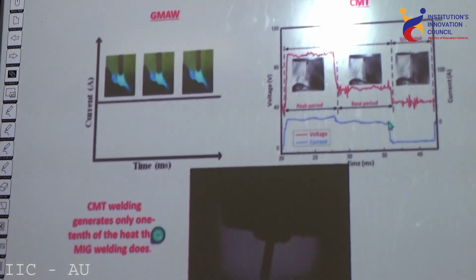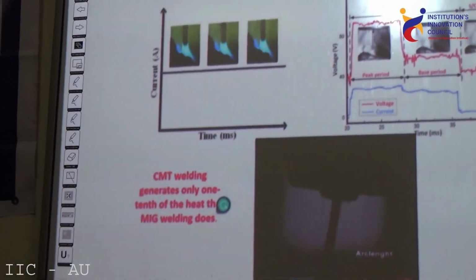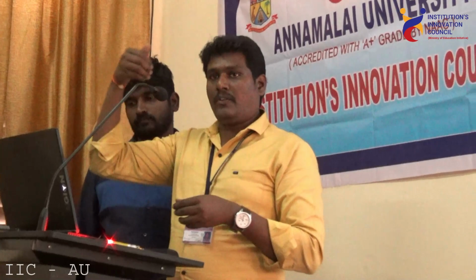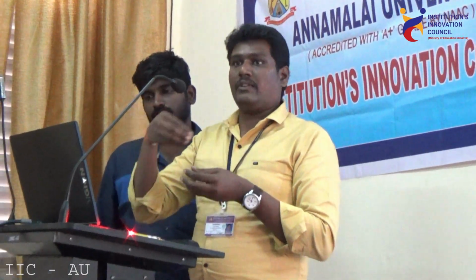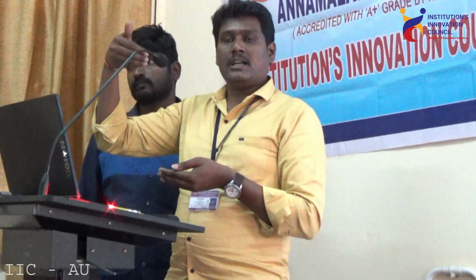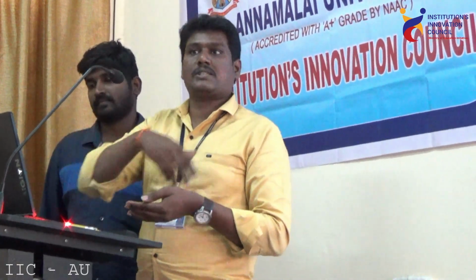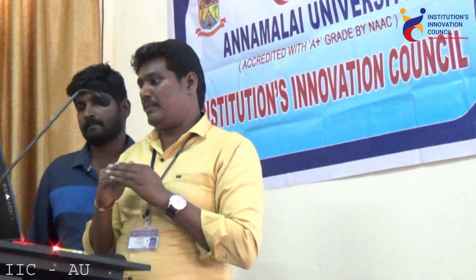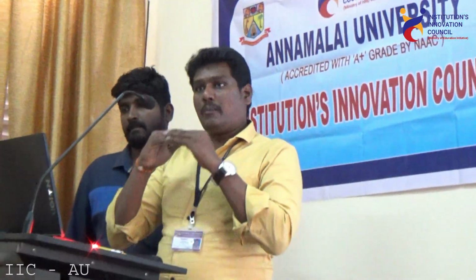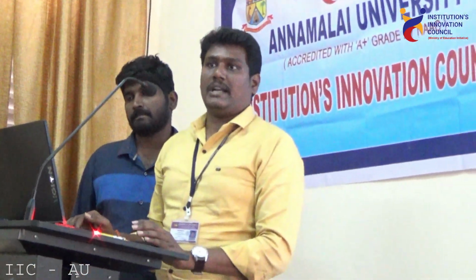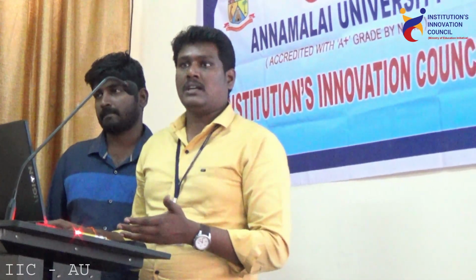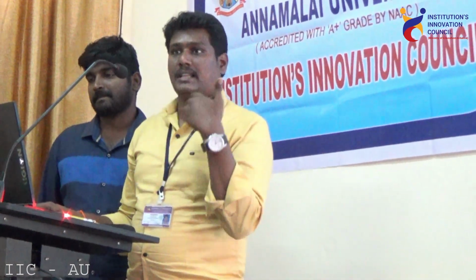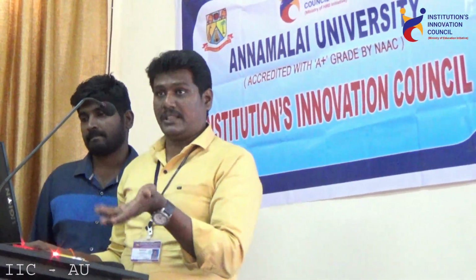What happens is, when the filler wire touches the base material, which means the substrate, the heat input reduces nearly to half. And when it moves away from the base material, because of the generated heat the filler wire will melt, and it will deposit as a layer on the substrate material. So this process will continue, and nearly half of the current input will be reduced. Because of that, the heat input of the process will be reduced in this type of welding process. So that is the major reason for the reduced heat input, which enhances the strength and other properties of the component produced with this process.